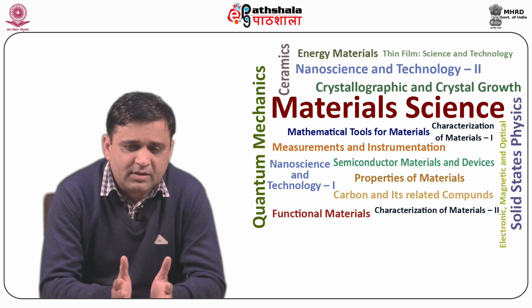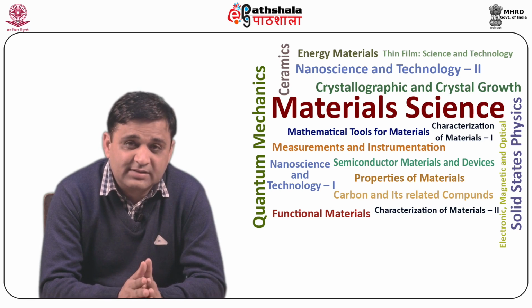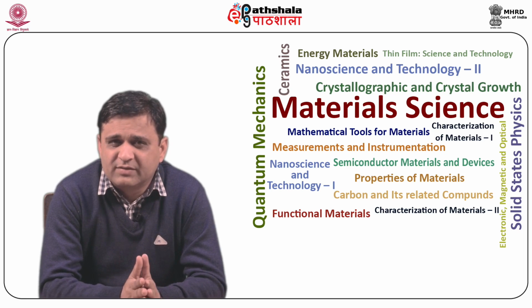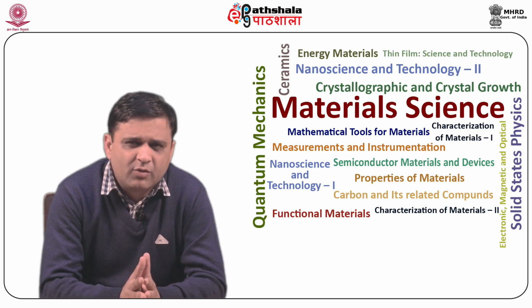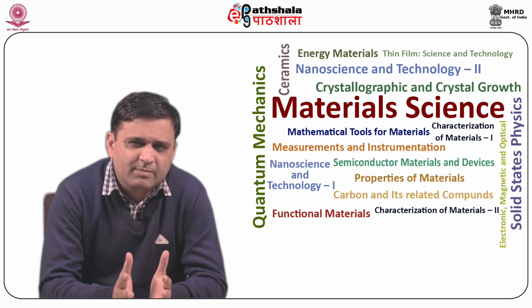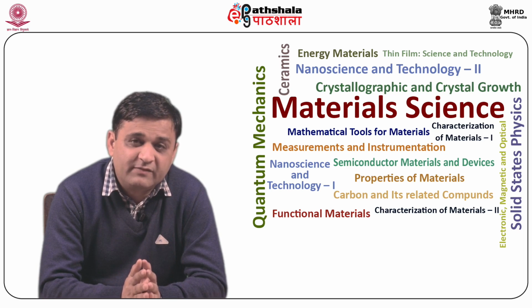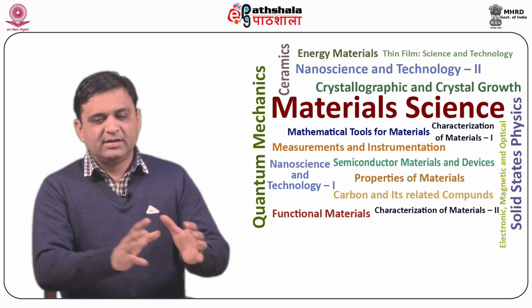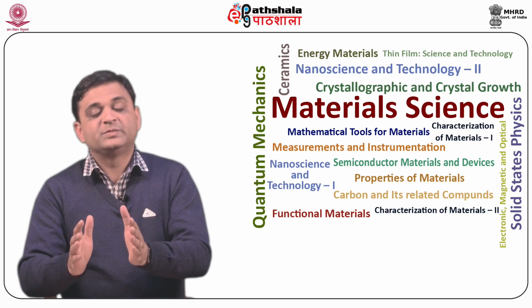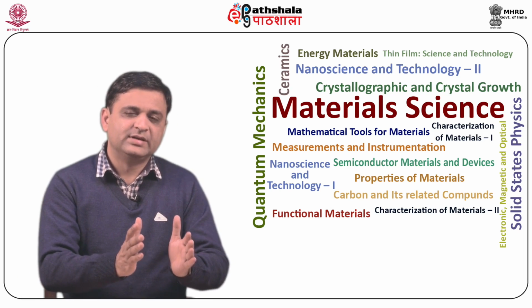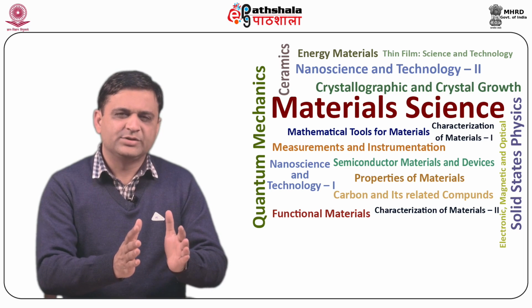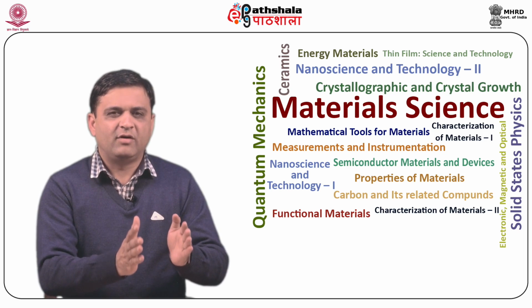So why the reciprocal lattice? As we have learned, scanning of X-rays, or should we say theta, is basically a mapping of your sample in reciprocal space. You are mapping your sample in reciprocal space. So the X-ray diffraction pattern that you obtain is the reciprocal space mapping. That is the purpose of defining a reciprocal space. If you understand the reciprocal space of a particular specimen, of a particular structure, then you can also get back its real space structure by applying the transformation formulas which we have already used.